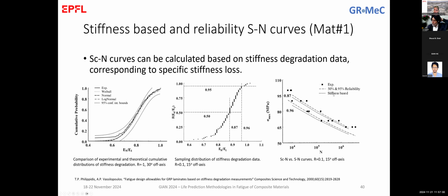And these values here, I selected not randomly, not without any prior analysis, but based on the model that I did on the stiffness degradation data, which, if you remember, we said follows a Weibull distribution. I can do this analysis with the Weibull distribution, but I can also use the experimental data directly and plot the distribution of the experimental data and check, for example, what value of stiffness degradation corresponds to 50% of this distribution, and what value corresponds to 95% of this distribution. And this is how I defined these levels.